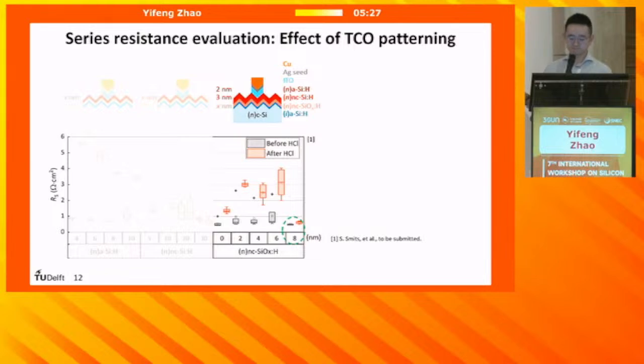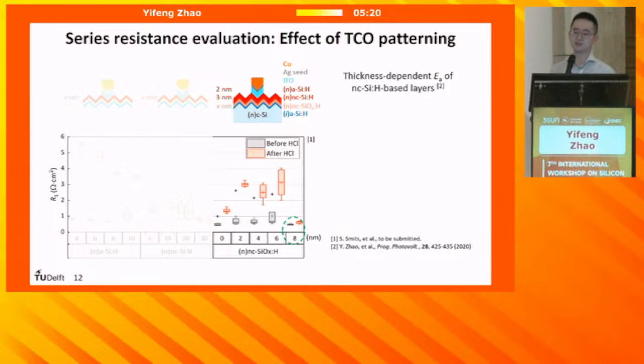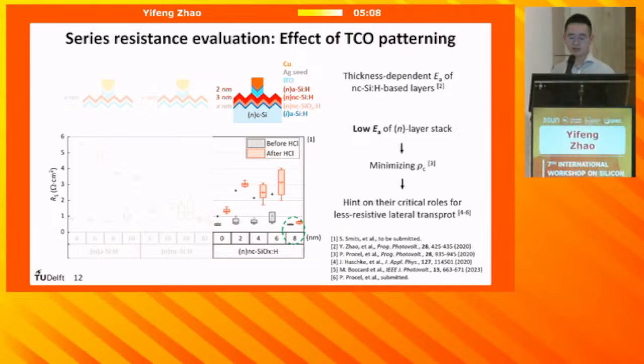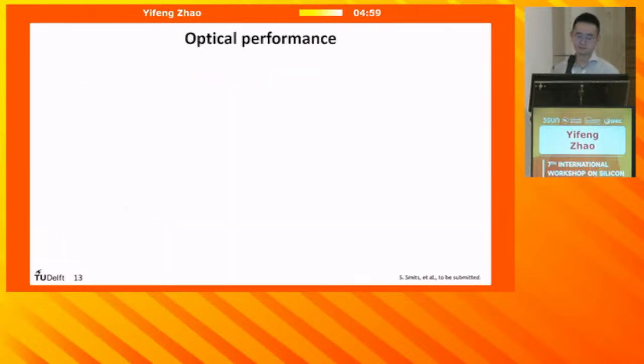It is known that nanocrystalline silicon-based materials have thickness-dependent conductivity or activation energy. Those results tell us that a low activation energy of the N-layer stack can minimize the contact resistivity, which might hint at the critical role for less resistive transport of electrons in a crystalline silicon wafer. So next, let's move to the optical performance analysis.